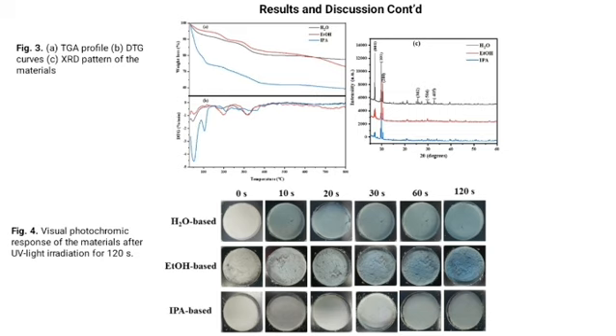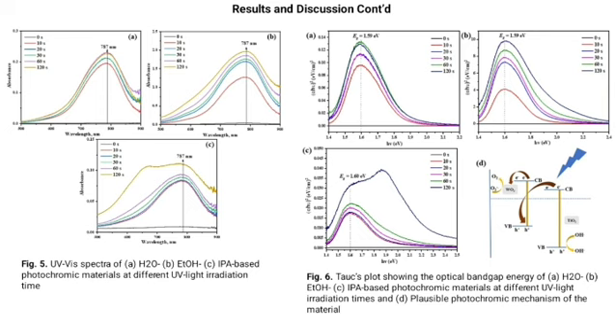Furthermore, for the optical and photochromic property of the materials, which was monitored using UV-visible spectroscopy, all the prepared tungsten oxide heterostructures optically change from white to blue under the UV light source, and the UV spectra of the materials before irradiation did not show an absorption peak, which could be due to the relaxation of the electrons and holes in the compound. However, after 10 seconds of UV light irradiation, there was a sharp electronic transition, giving rise to an intense absorption, which was captured at 787 nanometers. In all the materials, the water-based heterostructure displayed the fastest color formation after 10 seconds of UV light irradiation, which could be due to strong hydrogen bond interaction in the compound, thereby facilitating a photo-induced intermolecular long-range electron transfer process.